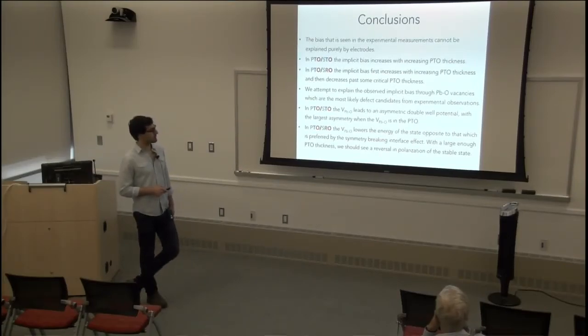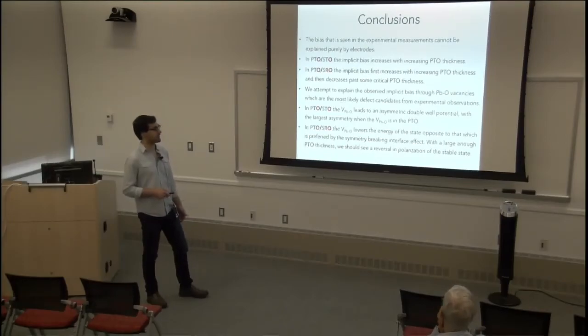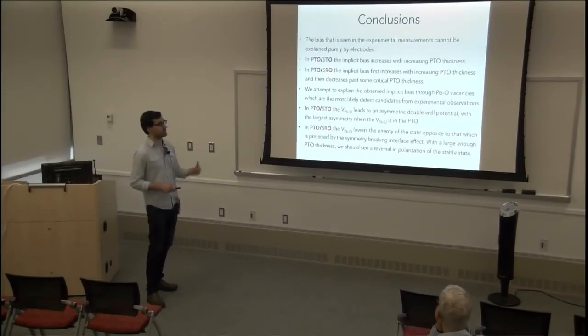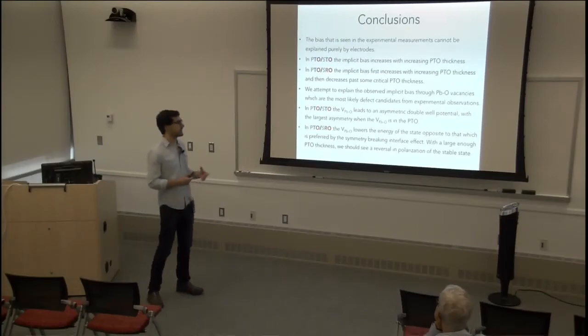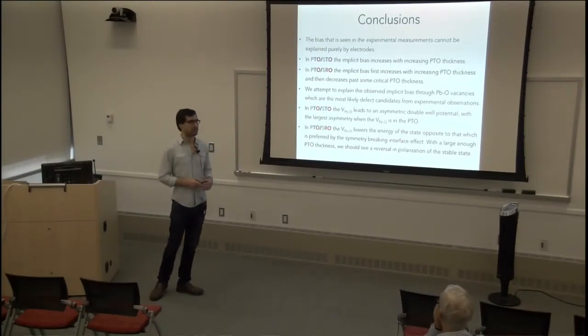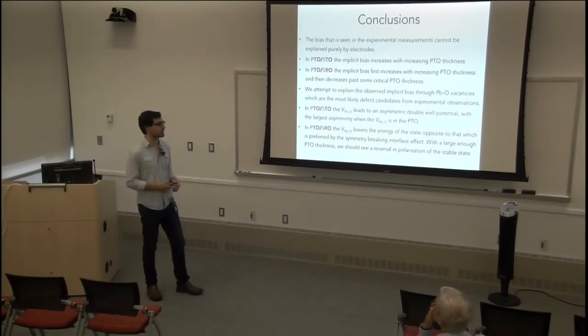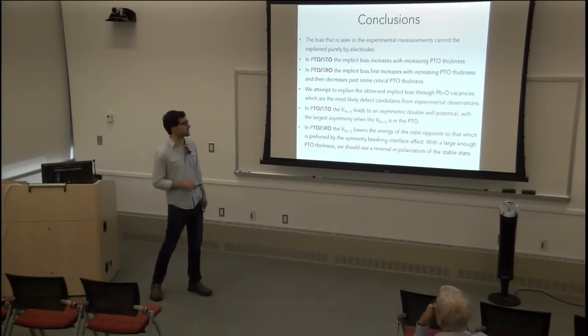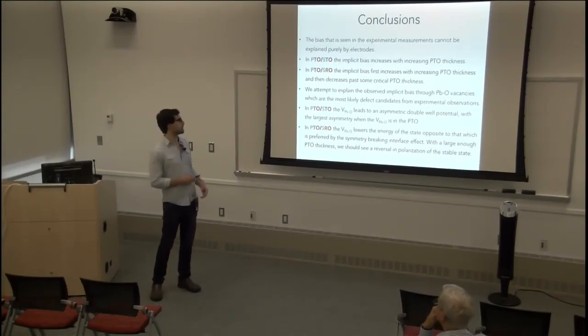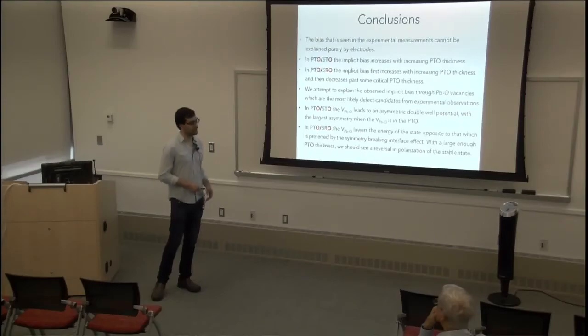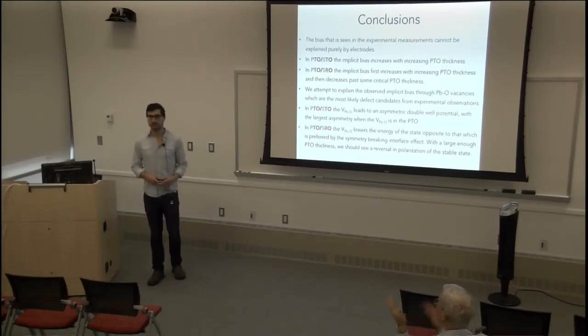what happens when you introduce this lead-oxygen divacancy in the interface is it lowers the state opposite to the one that was preferred by the symmetry breaking at the interface. So we believe, and we have to confirm this with a larger simulation, with a large enough lead titanate layer thickness, we should see a reversal in which state is preferred. That is, which state is the more stable state. And we believe, once we do this, we have a complete picture to explain the bias that's seen in both lead titanate, strontium titanate, and lead titanate, strontium ruthenate. Okay, thank you.